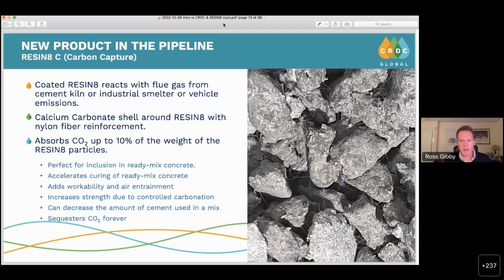And we also add some nylon fiber reinforcement there. And we take that, it's basically hot and active initially when the reaction happens with CO2. And we put that into ready-mix concrete, poured-in-place concrete, and it has incredible value. Not only does it accelerate curing through carbonation rather than hydration, but it increases strength. When it increases strength, it allows us to reduce the amount of cement used in that concrete mix. And you may know that cement has a very high carbon footprint, and it's also very expensive. So we can not only absorb and sequester CO2 with the particles themselves, but then we can use it to reduce the amount of cement used, which further reduces the carbon footprint.